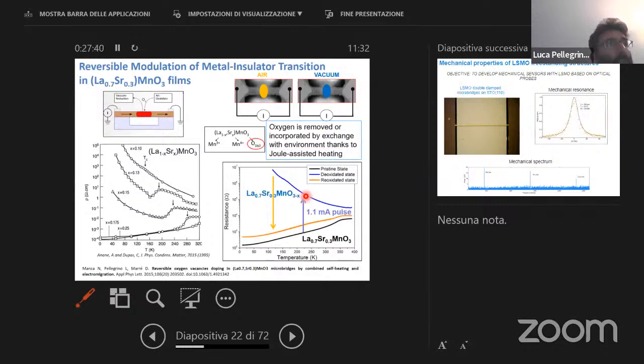As I showed you before, you heat up the sample to high temperature. We could not measure the temperature, but I guess it's above 600 degrees. You see the light coming from the sample. And you take out oxygen because you are in vacuum. And so you completely change not only the resistance, but even the magnetic behavior, because here you have a ferromagnetic metal, and then here you have an insulating non-magnetic compound. You have no magnetism in this place because the resistive behavior is associated to the magnetic behavior of the sample. Of course, you are tuning the properties only in this region where you increase the temperature.